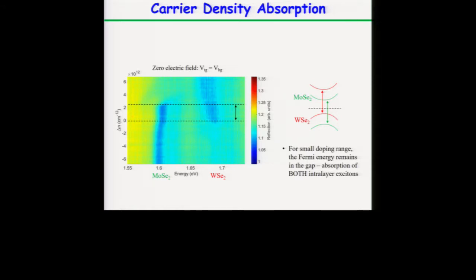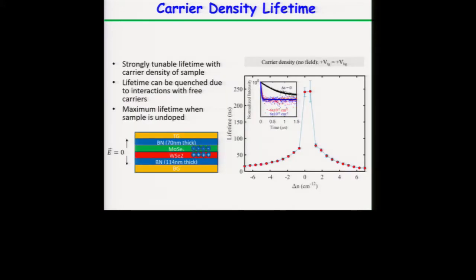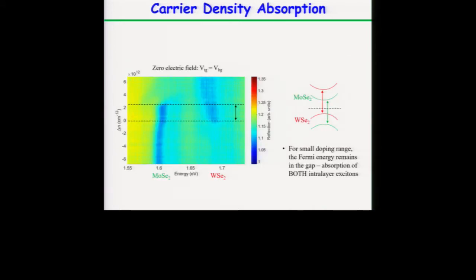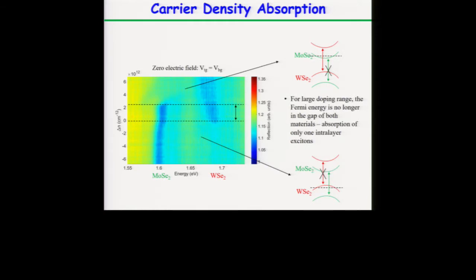So under these conditions we are doping MoSe2 while tungsten diselenide is still undoped. If we go to a negative voltage regime, MoSe2 is still undoped, while we are doping tungsten diselenide to a more p-type material. We only have a small window where the two samples are intrinsic. That's why we believe the lifetime is long in this small window when the samples are intrinsic, but once we start doping them, the lifetime reduces a lot. All right, this is the explanation I just gave.